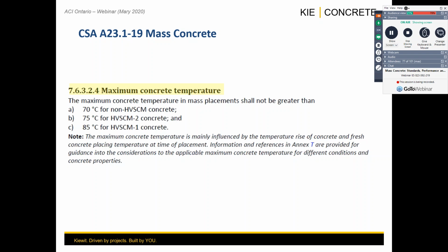HVSCM-2 is going to allow you to go up to 75 degrees Celsius. HVSCM-1 is going to allow you to go to 85 degrees Celsius, meaning that at that point you have, in many cases, 50% of your cementitious material already accounted for by SCMs, right? So in that case, you have an improvement in the chemistry of hydration. You obviously are already taking care of the chemistry of the cementitious materials, and given the research and the feedback from the academics within the committee, with all the research being done to date, and including ACI considerations, it was found that these numbers were going to be reasonable for the standard.